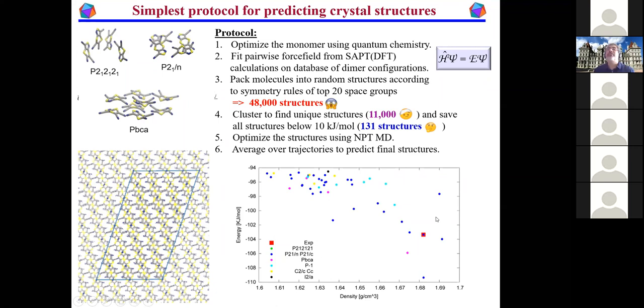Now, when you enter the competition, you don't know what the answer is, right? That's being kept from you. So this is why it's called a blind structure prediction test. But you submit your candidates, and then they'll tell you if you got a match to the experimental structure, which in our case turns out to be this red box here, right? It's not the lowest energy structure, and that could be because our force field is far from perfect, right? But we do get a match. Turns out it's our fourth ranked structure.